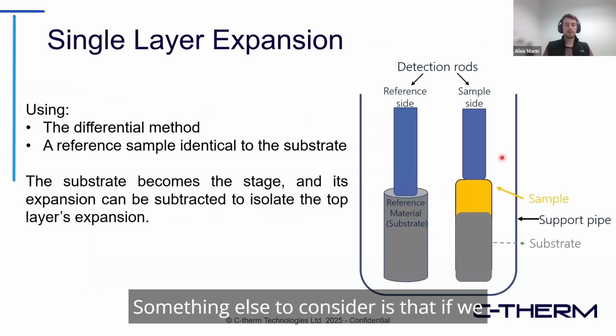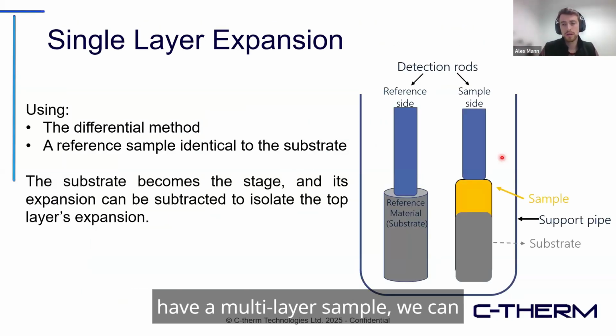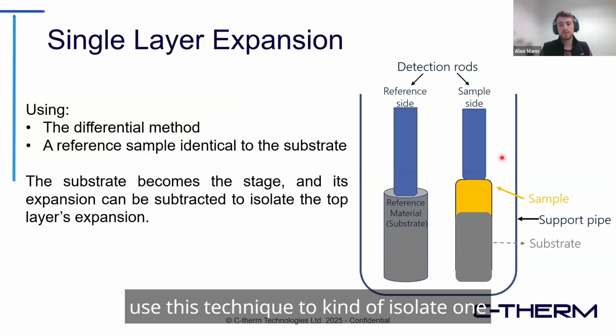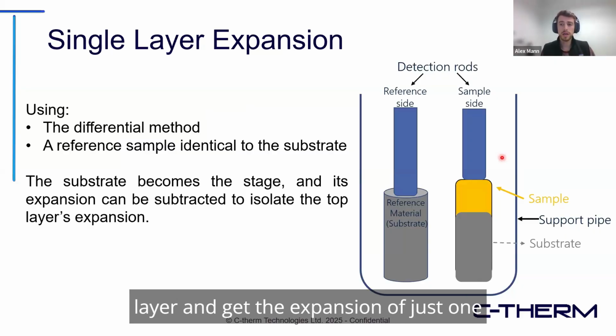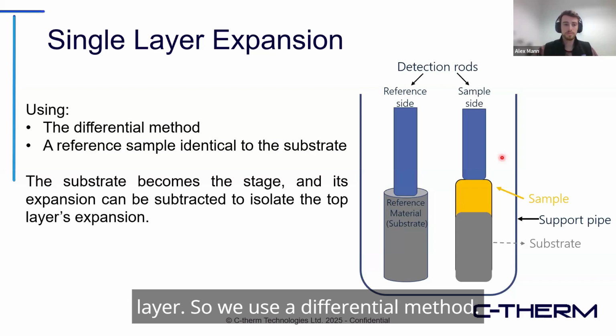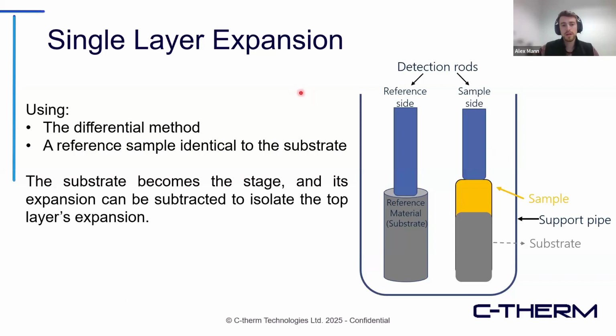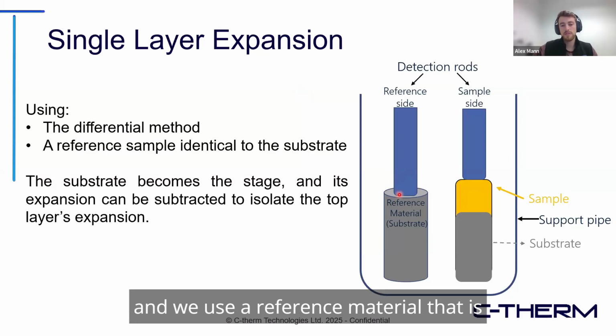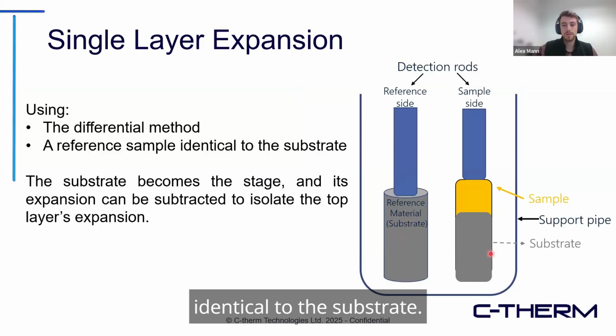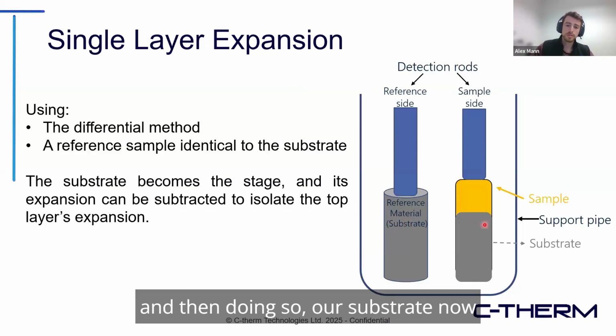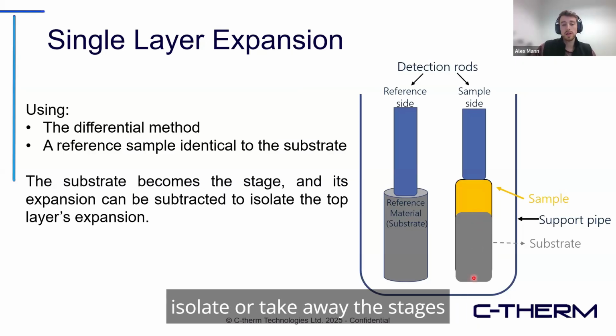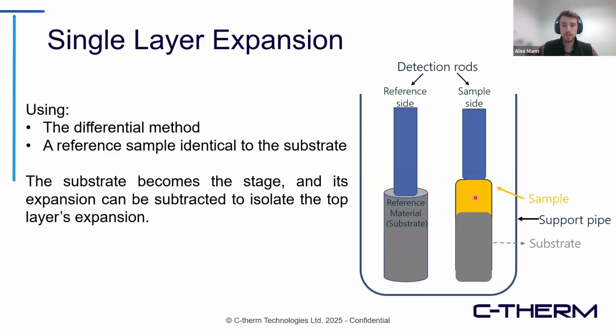Something else to consider is that if we have a multi-layer sample, we can use this technique to isolate one layer and get the expansion of just one layer. So we use a differential method, and we use a reference material that is identical to the substrate. And in doing so, our substrate now becomes a stage, and then we can take away the stage's expansion, and then just get the expansion of our sample.